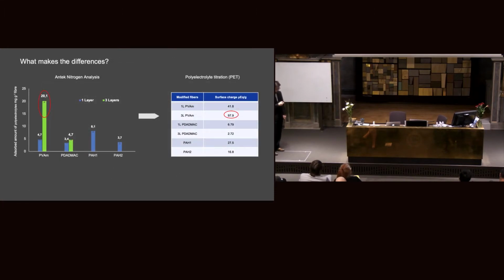What makes the difference between these different cationic polyelectrolytes? Using nitrogen analysis, we can see there is much more adsorbed PVAm on the 3-layer modified samples. But the adsorbed amount doesn't strictly correlate with antibacterial properties, because if you have a large adsorbed amount but the charges are all neutralized by the previous layer, it should not work.